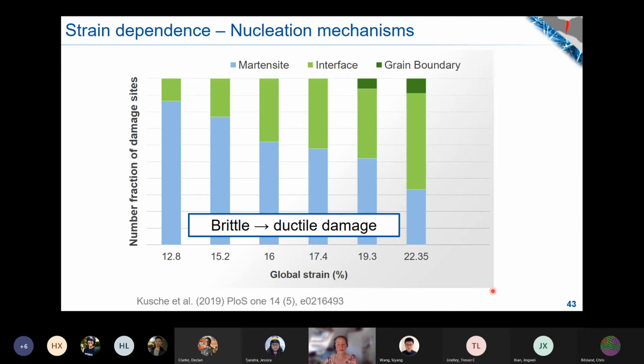To show you an idea of what we've done with this, we looked at an industrial dual phase steel. We deformed it to different strains, and we wanted to know which mechanism actually dominates damage here. We get a number fraction of damage sites. With global strain, the number of sites goes up nearly exponentially, from a few hundred to thousands of damage sites over our panoramic image. What was striking was that initially we are completely dominated by martensite cracking, and then later we get a lot of interface dominated mechanisms.